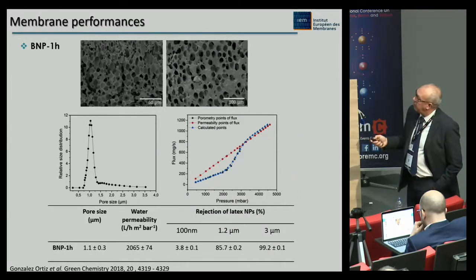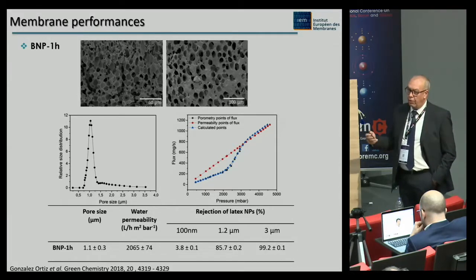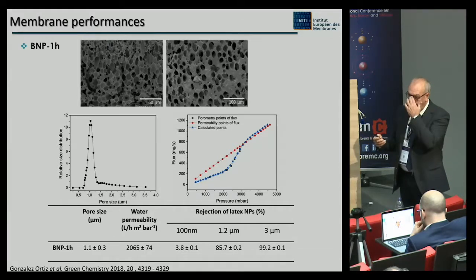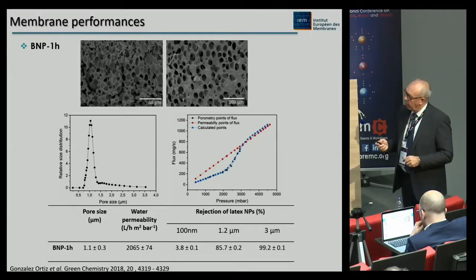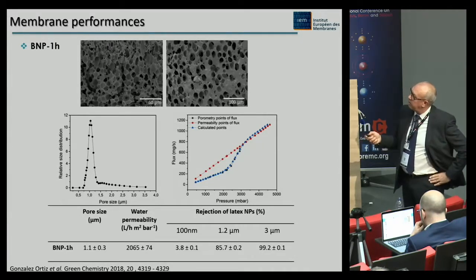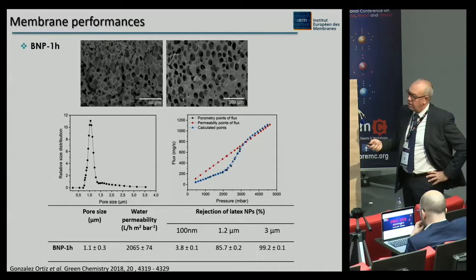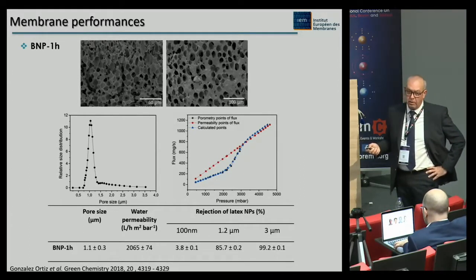Now, the test of permeability and also of rejection, in order to characterize the pore size of the membrane. If you take this membrane prepared after a curing time of 1 hour, the mean pore size is around 1 micrometer. The water permeability is very high, 2,000 liters per hour, square meter, and per bar. And you can see that the rejection of the latex is very good for particles with 3 micrometers in diameter.